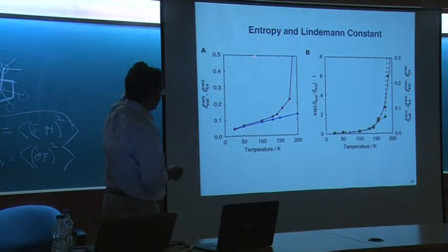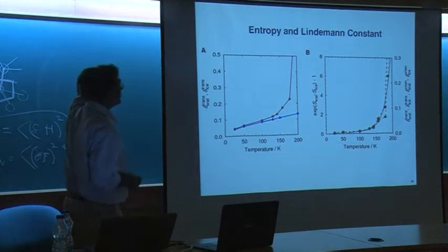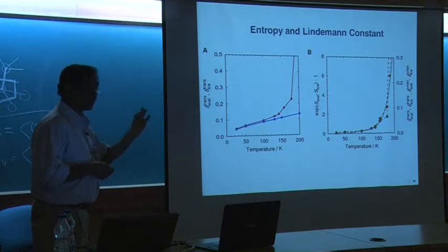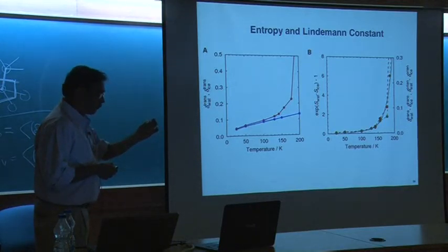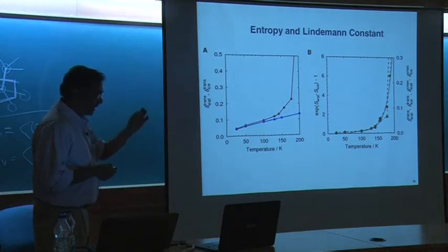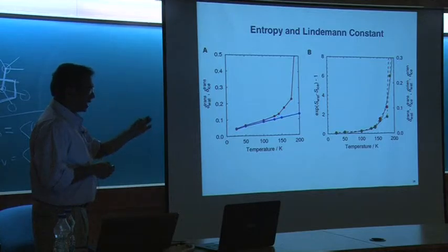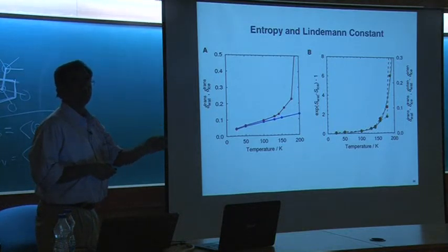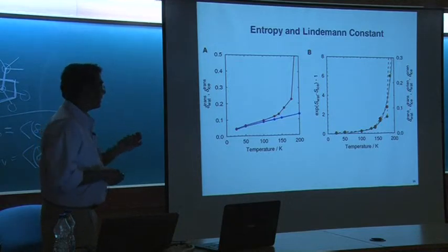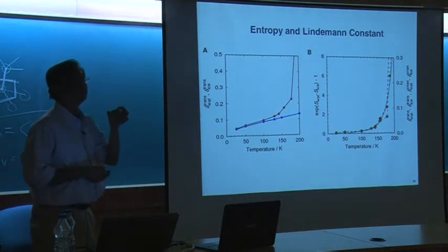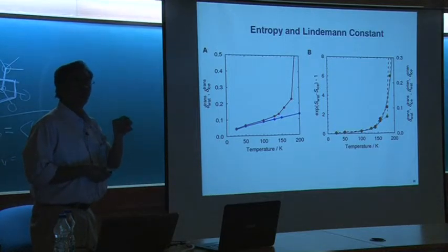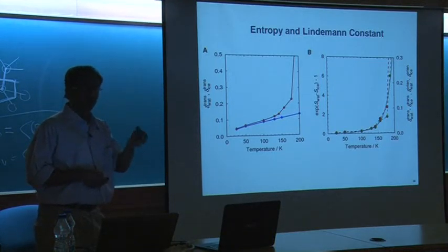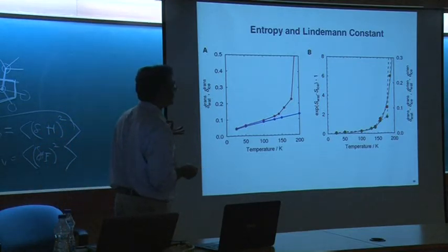This picture is that there is a constant called the Lindemann constant, which is a mean square displacement. That means you take a particle, get its average position, things are very slow, you can define an average position, and then it oscillates, and you find out how much is the displacement. When a solid melts, that displacement grows very quickly, and when it becomes 10% of the cell length, that's where it melts. That's called the Lindemann constant or Lindemann ratio. It's a phenomenology which is obeyed by almost all solids. It's a universal characteristic. Chemists are not used to universality, but physicists refuse to talk of details. They will talk of universality. Now, universality is far more interesting than the details. It's far more interesting than doing a quantum calculation up to the second decimal place. These are really big problems that I am talking about here today.